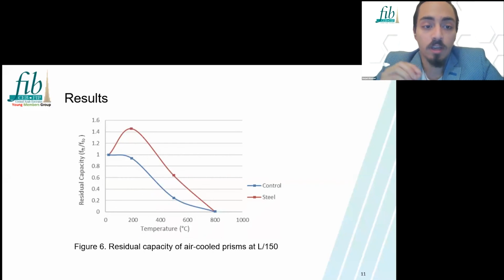Now onto the residual capacity of the concrete. In terms of flexural strength, which is what we studied, we found that the control specimens started to lose their strength as soon as the heating started. However, as shown in figure 6, there was a 45% increase in the flexural strength of steel fiber lightweight concrete specimens at 200 degrees. Then they started to lose their strength again until at 800 degrees Celsius, both of them failed completely with no strength at all.